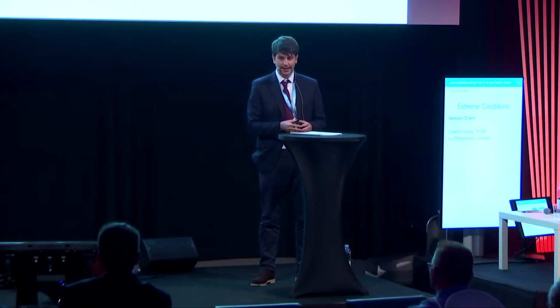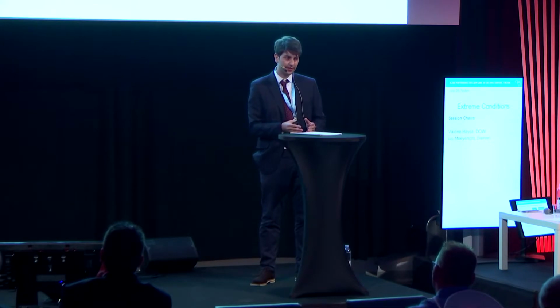However, as the aim in this case is to present simplified models, and we have tried to avoid at this stage determining the lamination length, we have decided to use material properties that have been derived from experiments. So we've used the experiments performed by Hooper, and they have defined in the post-fracture state yield strength values, strain failures, and initial Young's modulus. These were tensile tests performed at high strain rates on pre-fractured laminated glass specimens, including a uniform cracking pattern of 10 millimeter length of fragments.